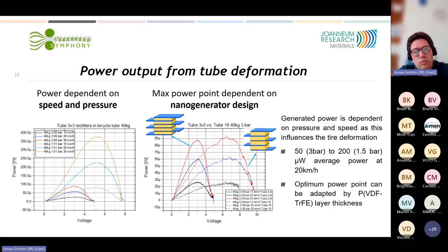The only difference between these two harvesters is that on the left side, there is five layers with a thin PVDF-TrFE. On the right side, there is four layers with a little bit thicker PVDF-TrFE. And by this, of course, we shift the maximum power point quite a lot. And as our electronics is working at 3.6 volt, we cycle the storage cap between 2 and 3.6 volts. So with this adaptation of layer thickness, we directly get at this working voltage an increase of a factor of 2.